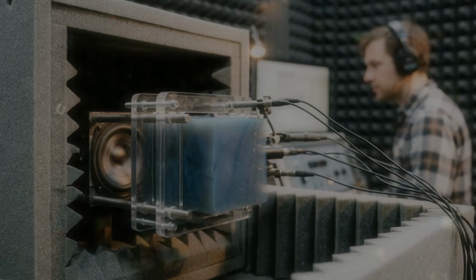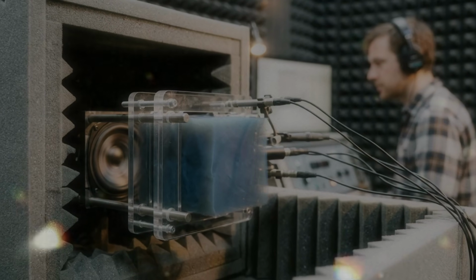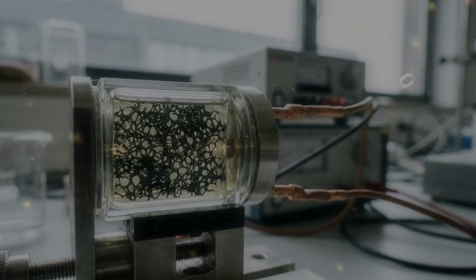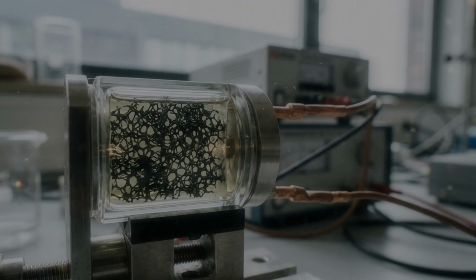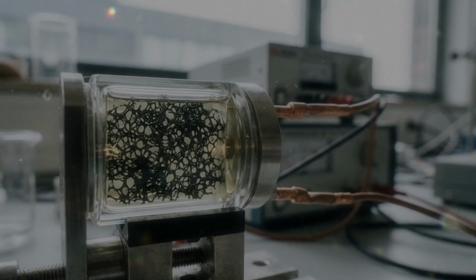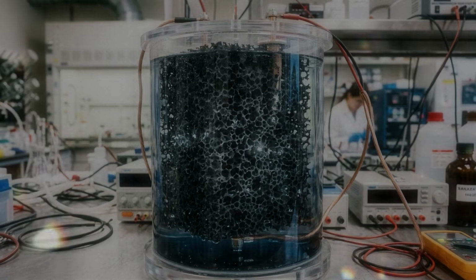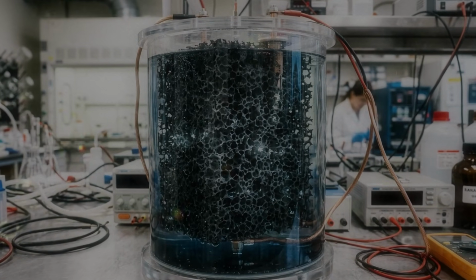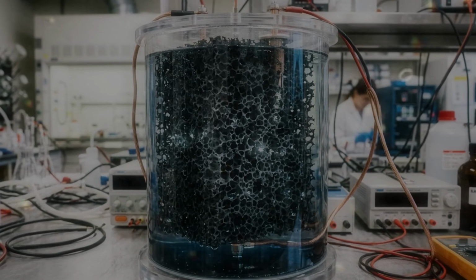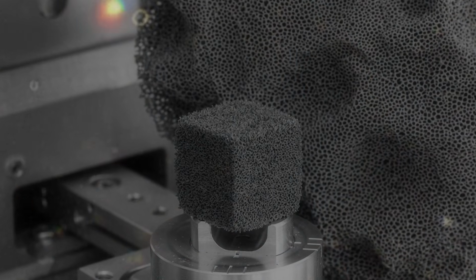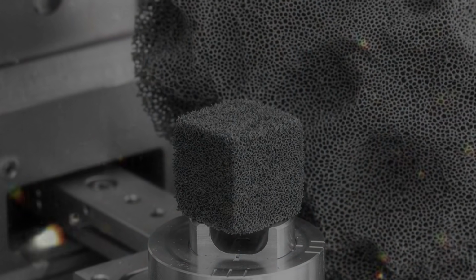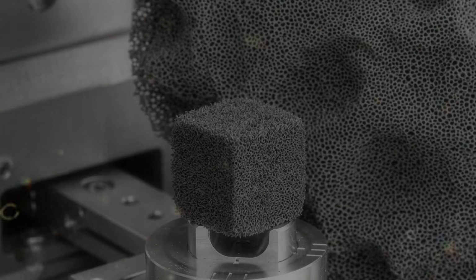The pressure cannot simply be dropped without control. A rapid release may cool the system, create uneven forces, or damage the sample. The fluid must leave the tiny pores gradually. When the vessel finally returns to ordinary conditions, the gel has become an aerogel. The liquid is gone, gas fills the pores, and much of the original solid skeleton remains.